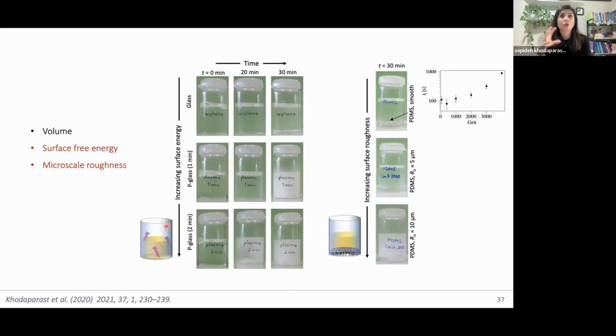If we go to a larger scale, all of the conclusions I was making under a microscope still hold. In a larger container, if you plasma treat your glass container, you start seeing crystals forming. Compare these cases on the right from top to bottom: no plasma glass, then plasma-treated glass for a longer time, and you see more and more crystals forming. Now, if you add a rough surface to your container and tune the surface roughness, you can increase the amount of crystallization that you get.